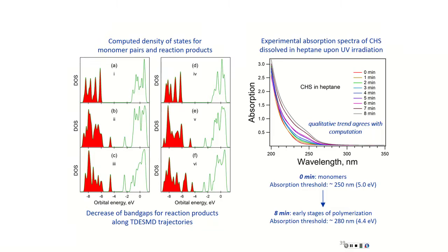Well, we all like exploring density of states. Originally, density of states gives a gap of 4 eV, and as we go through this association, it shrinks. Well, in calculation with DFT, which is a little substandard to predict gaps, it shrinks too much. It gives just a qualitative trend of larger cluster, shorter gap. In fact, in the experimental observation of the first steps of the reaction, it goes through minutes rather than hundreds of femtoseconds because they have lower intensity, and in simulation we exaggerate the intensity. It shifts to the red part much more conservatively, not as in calculations, but the trend is there. So the longer the reaction goes, the redder becomes the spectrum.